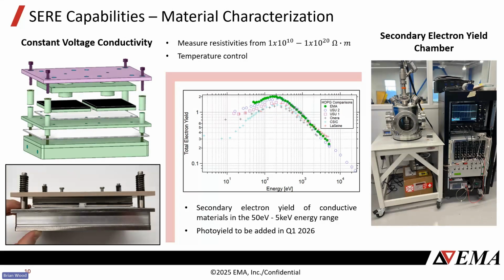It's pretty straightforward in theory. The problem is that you're trying to do this on extremely insulative dielectrics, so you need to do this in vacuum, reduce all the noise in your system, and have a very sensitive electrometer. You need a battery power supply so that there's no ripple in your applied voltage, and after all that, you're able to accurately measure the conductivity of these insulators that are commonly used in space.